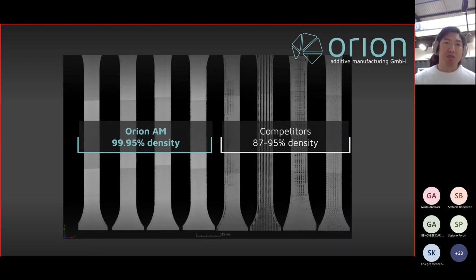The other part of it is that our process is able to achieve a really high density. Whether it's for implant applications or railway applications or space applications, this density has a major impact on the structural integrity of the part. In some cases, especially in space, if you have internal porosities or voids, this can be quite problematic because of off-gassing. If you have air or a gas trapped inside, once you launch it out into space, if this gas leaks out, it can be very problematic to scientific instruments or sensors, where some of this gas comes out of the material and then accumulates onto these instruments. We're able to prove that we have a void content of less than 0.05%, which is on par with injection molding and CNC machining, which makes it useful for validating our process in comparison to these other traditional manufacturing methods.